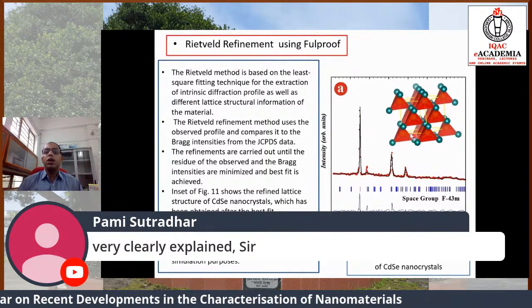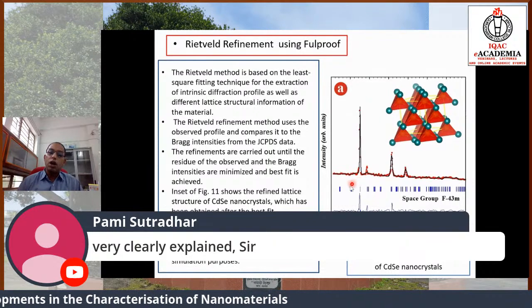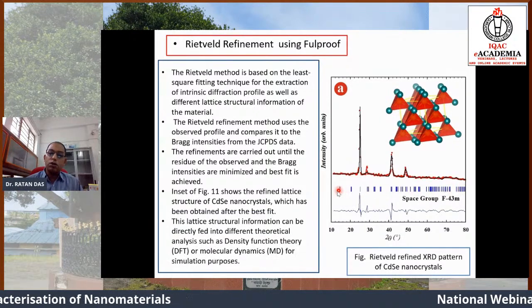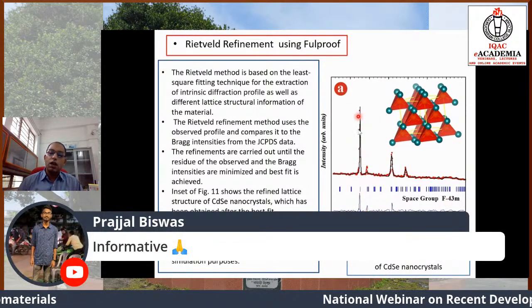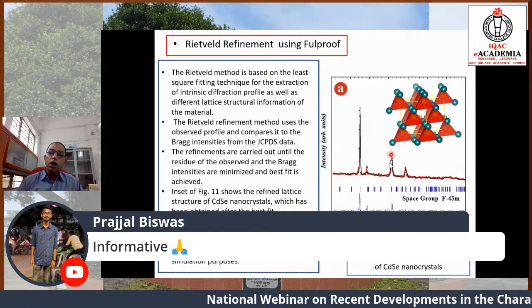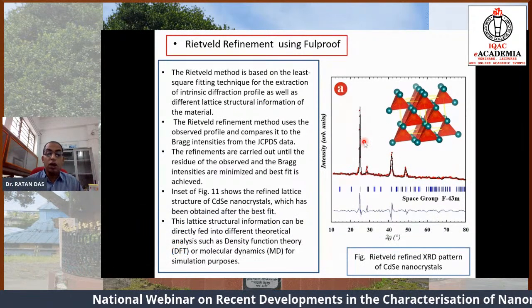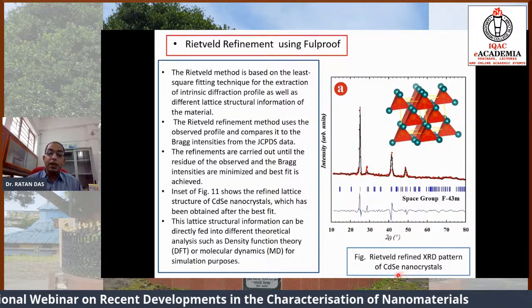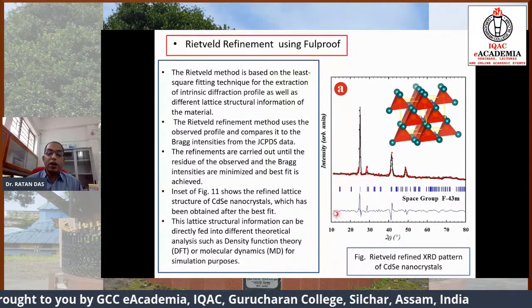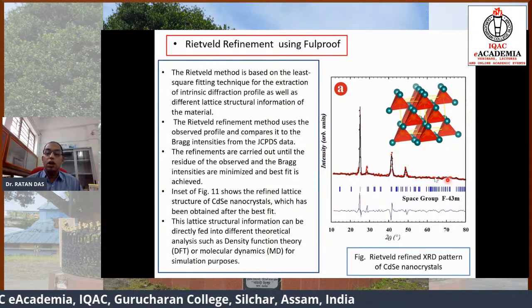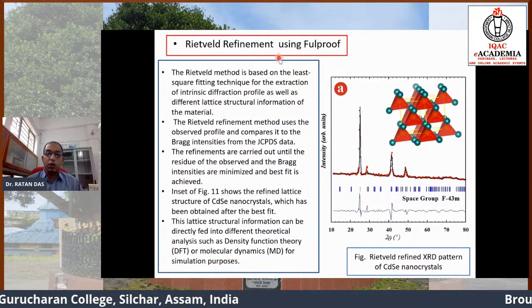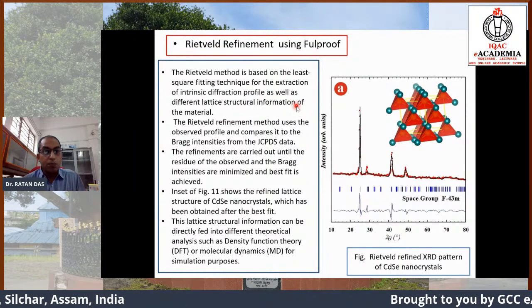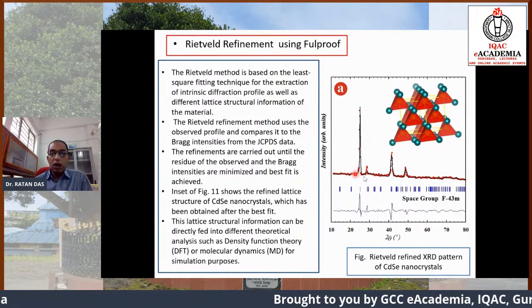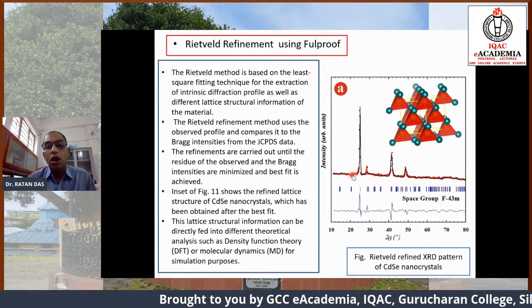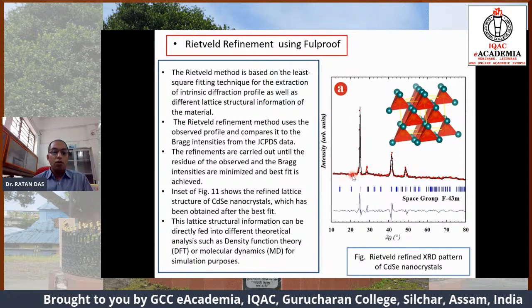In the refinement, we also obtain the crystal structures and the standing lines, all the standing lines that are available for that particular material. And there is some background we can also obtain in the case of Rietveld refinement. Earlier I told you that background is very important, so here background matching is also required to be furnished.